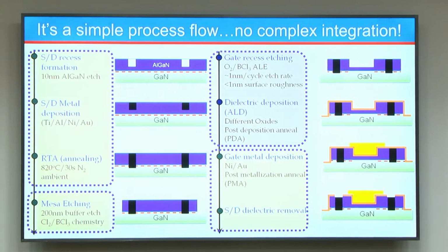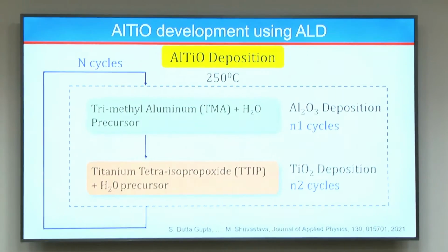So this is the simpler D mode like process, where you have the source drain first. So you do the source drain contacts, then you have the gate stack deposited, and in this case, even for improving the source drain contact resistance, we had developed a recessed contact here, and then we had also developed a gate stack where the partial recess of the gate region was optional, and I will tell you later why the partial recess of the gate region was done. So it is a simpler process compared to the pGaN process, right.